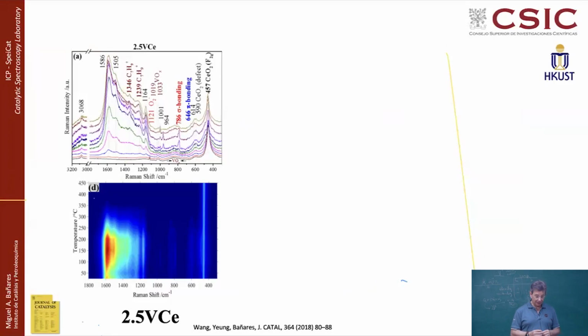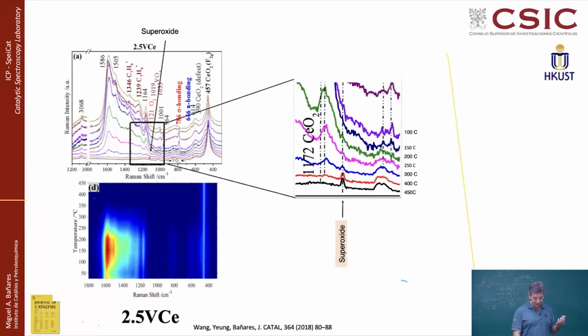There is something that I would also like to recall, because some years ago, before this work, we had seen how the vanadia ceria interface results in a very strong interaction. And you remember from before the coffee that cerium-3 is reduced at the interface with vanadium. And the Raman spectra during reaction is showing something there, hardly visible, which is the presence of superoxide species. Now, superoxide species typically appear when molecular oxygen adsorbs on the defects of ceria at very low temperature.